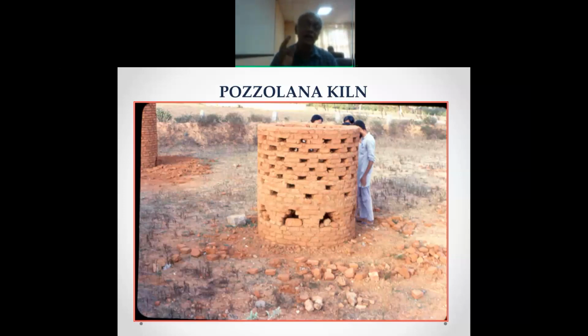If you burn rice husk at a high temperature, it won't be pozzolanic. If you burn it at a temperature below 700, the ash becomes pozzolanic. And burnt clay is also pozzolanic. We produce what is called combination pozzolana. We make briquettes with rice husk and clay, burn them here because the rice husk is the fuel, and then you grind it to 90 micron fineness. You have an excellent pozzolana produced in the village.